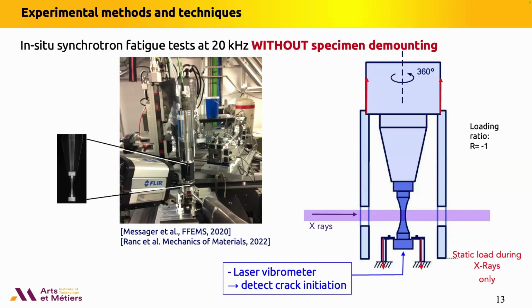So to do that, we have decided to mount the system on a tube, and the tube is loaded vertically here by an electromechanical system, and the specimen with a special geometry here with a shoulder is put in contact with a load cell in order to apply the quasi-static loading when there is an X-ray. When there is no X-ray, in order to automatically detect the crack, we use a laser vibrometer that is monitoring the vibration of the specimen at the free end here. And by monitoring with a fast Fourier transform in real time the appearance of second and third harmonics, which means the nonlinearity of the system due to crack initiation, we are able to detect a crack of typically 100 micrometer.